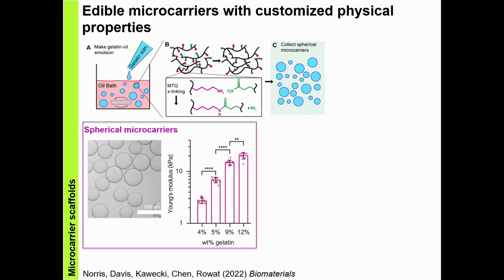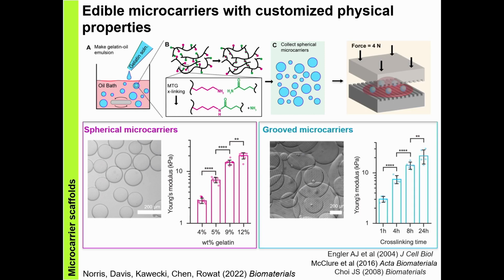So we also wanted to test the effect of topology of the microcarriers, because we also know from mechanobiology studies that aligned topologies can guide and promote the formation of myotubes. So we developed a process to make grooved microcarriers simply by templating the particles, squishing them between templates that we fabricate using soft lithography. And this created these grooved microcarriers that are like pancakes with grooves that are about 10 microns in width. We can tune the stiffness of these microcarriers as well, again, to match the optimal stiffnesses of matrices that have been found to be optimal for proliferation and differentiation.